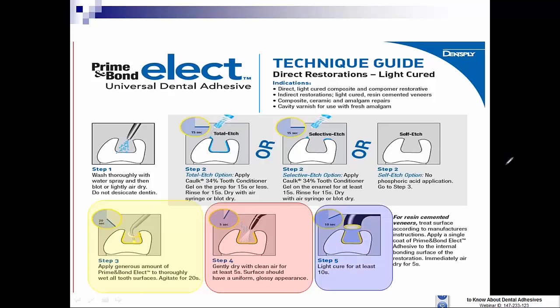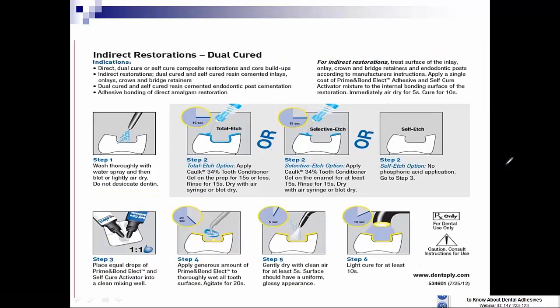And then something that's often overlooked is light curing. Sometimes 10 seconds of light curing in a deep cavity or a complicated cavity where there are parallel walls to the light will not be adequate. Sometimes 20 seconds of light curing for the adhesive might be indicated from two different directions to fully polymerize, visible light polymerize an adhesive in a complicated cavity prep.